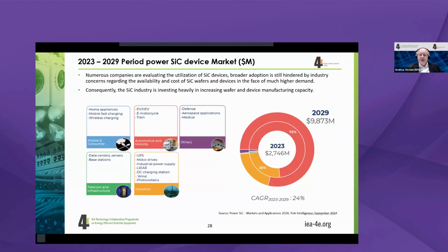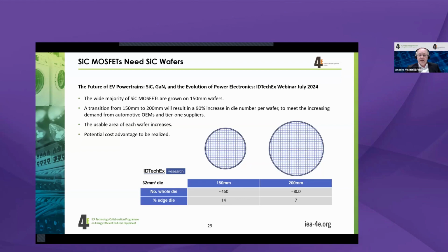Now, it means that as we foresee a large increase in demand, it is also clear that the silicon carbide industry has started to heavily invest in increasing the wafer and device manufacturing capacity. And one of the key points here is that there is a move from the wafer size 6-inch, which is 150 millimeters, to 8-inch. And while this is a relatively small size increase, the increase in die sizes which you can put on that surface is almost doubling. So that's a 90% increase. And that gives us a much better yield. The usable area has increased, and the cost advantage is very high.